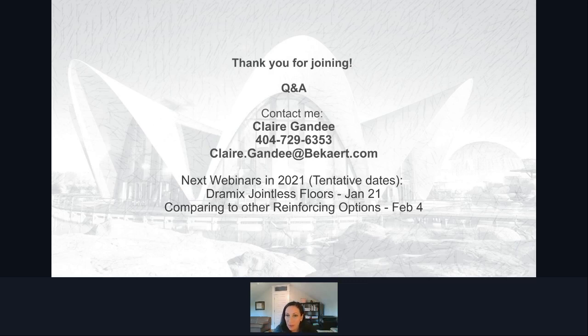Next question. I am currently working with fiber reinforced alkali activated concrete and performing 3-point bending tests, EN 14651, with Dramix 4D and 5D. Awesome. During the test, fiber rupture occurred with relative drop in applied load. Is rupture of the fiber suitable in flexural behavior, or for structural behavior, or pullout is the best mechanism to be achieved? What can cause a rupture? Can it be due to the fiber matrix interface in the right?